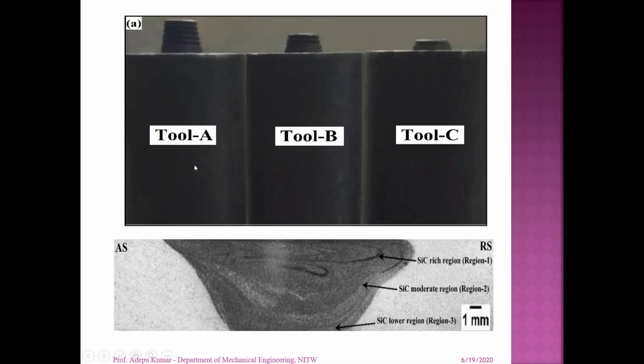This is one of the scholars' work. He has done the friction stir deposition process to develop functionally graded materials with silicon carbide volume percentage variation from the bottom to the top, using tool A, tool B and tool C. He applied the same technique which I showed in the last slide, and he could achieve different volume percentages in the thickness direction. You can see the silicon carbide in region 3, region 2 and region 1, and analyze the volume percentage of each region.